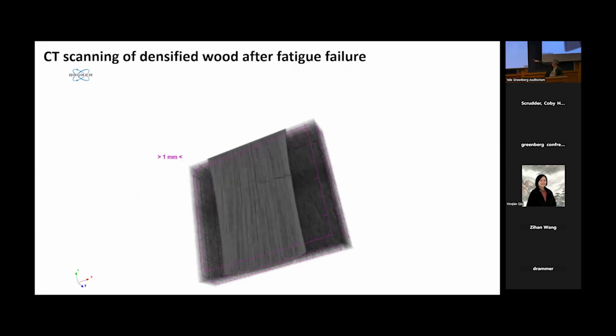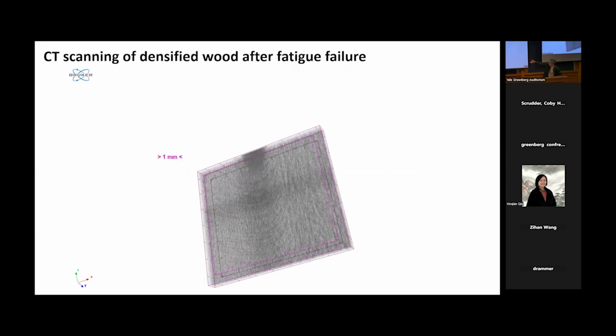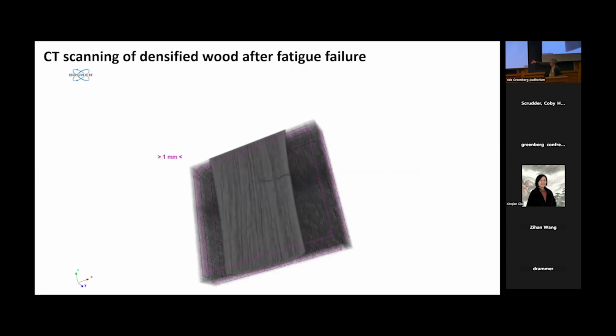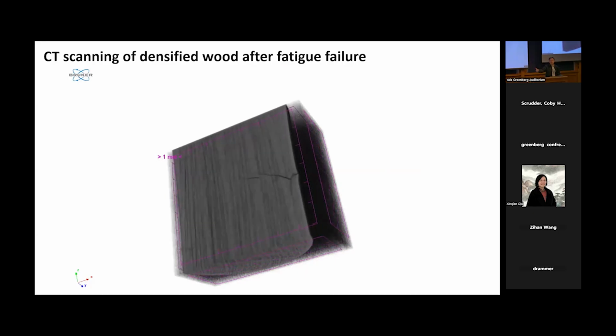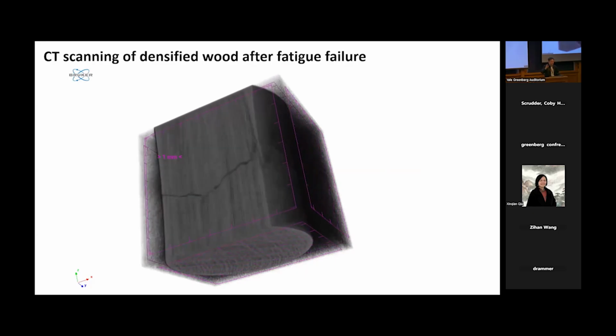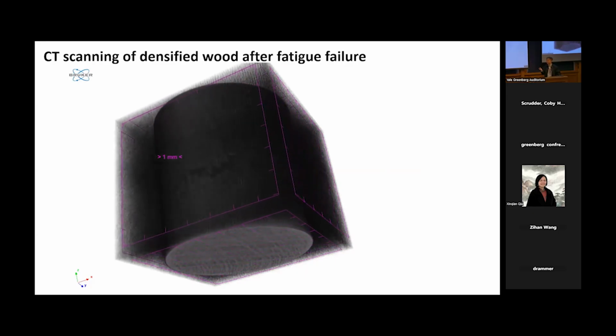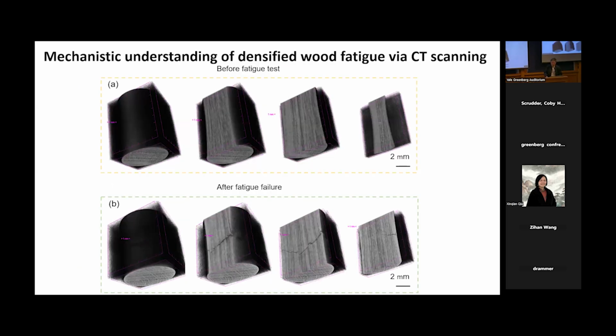But later on, at the other side, the back of the scanning, the crack is not running through the whole cross section. Roughly speaking, about a quarter of the cross section did not really fail or fracture when the fatigue failure occurred. And that's why it's holding together, because densified wood or compressed wood is so strong that even with a quarter of the unfractured cross section, it remains as one piece.